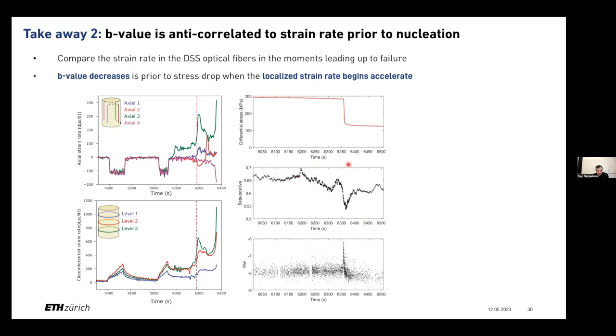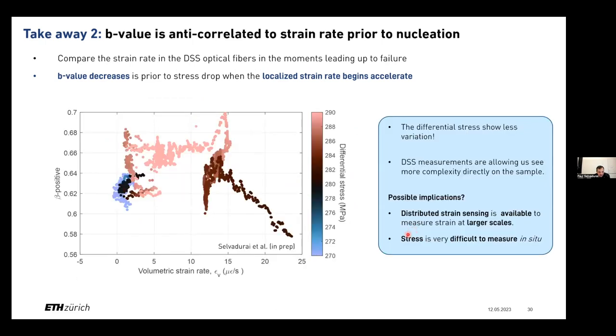So what we're doing right now is comparing the local strain rate to the B value, beta positive, analogous to the B value decrease. And we see that prior to or close to nucleation, the B value is relatively insensitive to the differential stress and starts to decrease. What we're plotting here is the volumetric strain rate versus the beta positive. In these last moments before failure, we saw this anti-correlation that we're investigating in more detail right now.